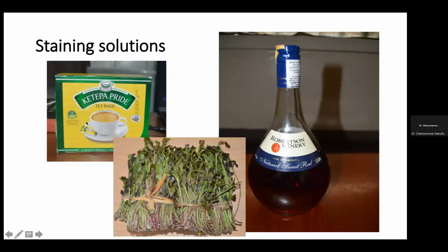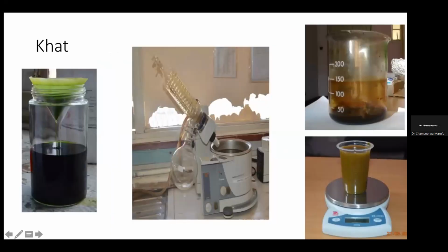So the tea solution, you just simply prepare tea based on the manufacturer's instruction. And then the red wine was used as it is. And then for the khat, we had to make a plant extract. We followed the methanolic plant extract, which is used in most studies which utilize plant extracts. So how we get the extract is you chop the khat into small pieces, you mix it with the methanol, and then you put it in a sonicator, and then you filter to get the solution indicated in the first picture.